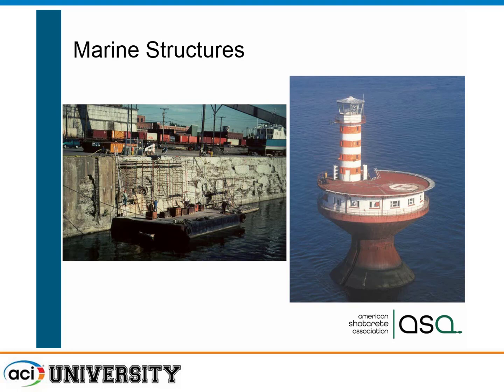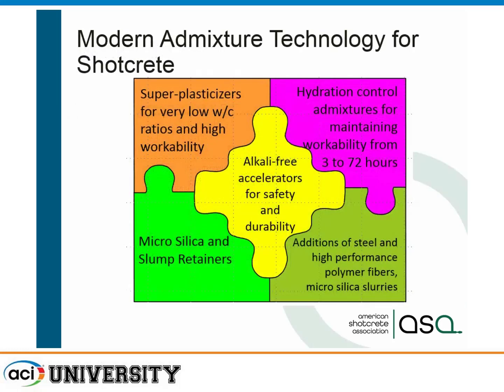Here, because this is a concrete base, a lot of deterioration between the high water line and the low. So what they did, they came in, shot off rubber rafts at low tide with an accelerator, got it in place, and strengthened that without having to worry about form work. Basically, we brought our concrete batch plants out there by using pre-mixed bag materials. And shotcrete's one of the most sophisticated users of concrete.